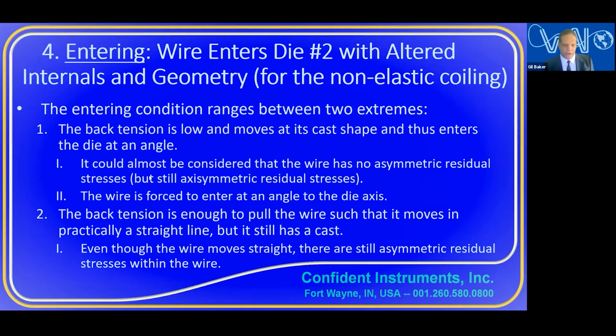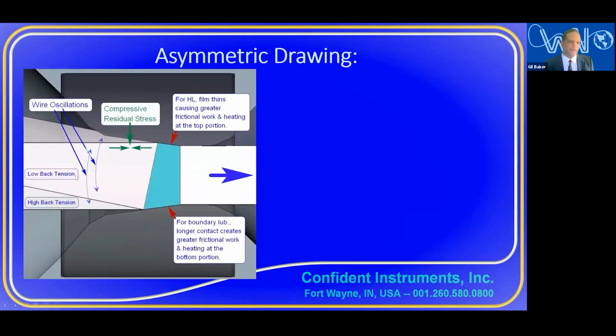And even though the wire moves straight, it's not that simple, because here in the bottom one, we're assuming the wire is moving in straight. But because of, for example, compressive residual stresses, again, asymmetric residual stresses, it causes a change in the deformation zone. It's not the neat deformation zone we typically see that's trapezoidal. And you see that this angle is different. Well, here where there's compressive residual stresses, it's harder for the wire to yield. It's harder to get to a yield criterion. So the wire is waiting to yield until the stresses are built up to cause it to yield. Down here, where there's maybe some tension or let's say no residual stresses at all, the wire can yield faster. So it changes the shape of the deformation zone.